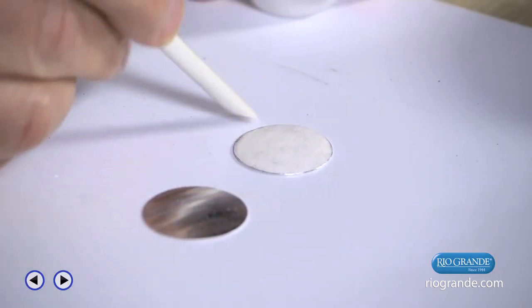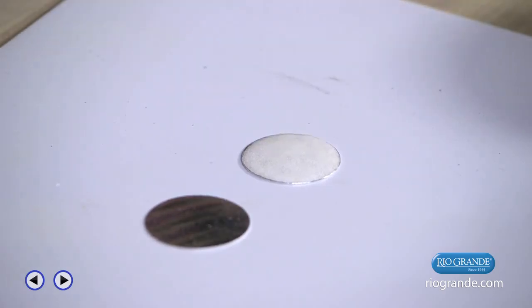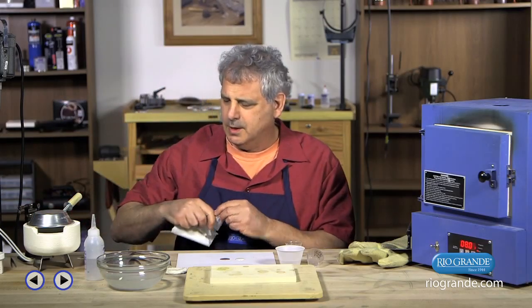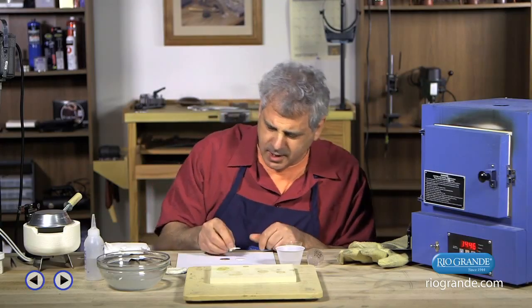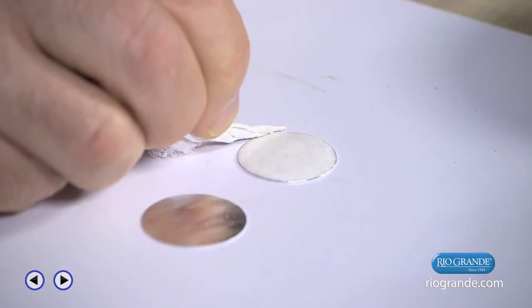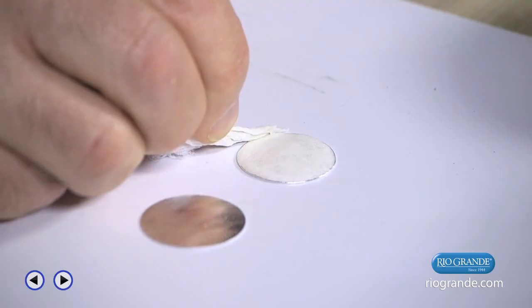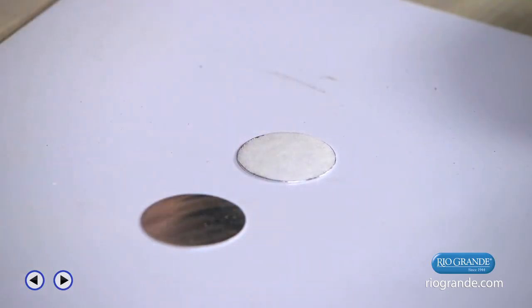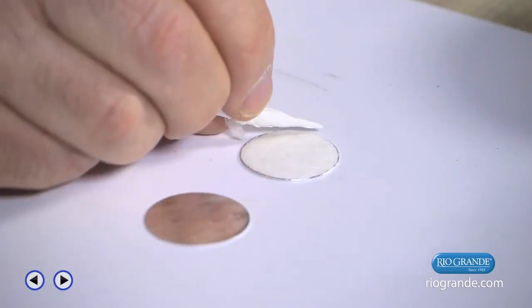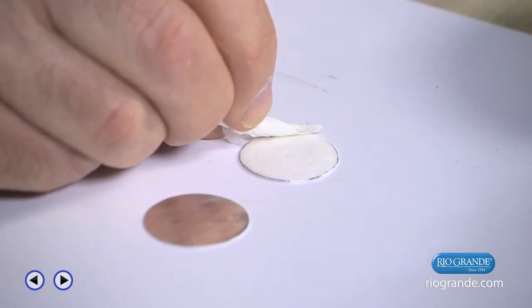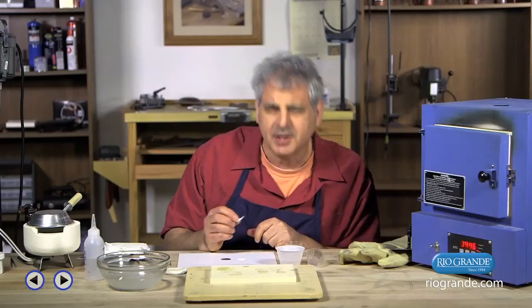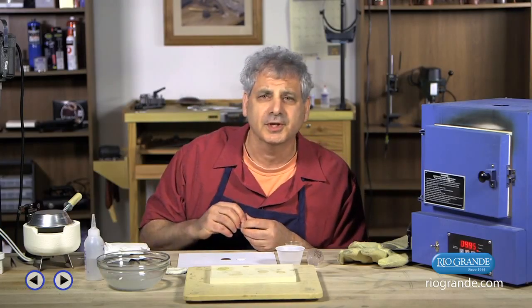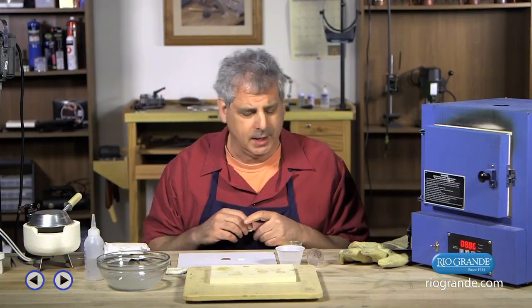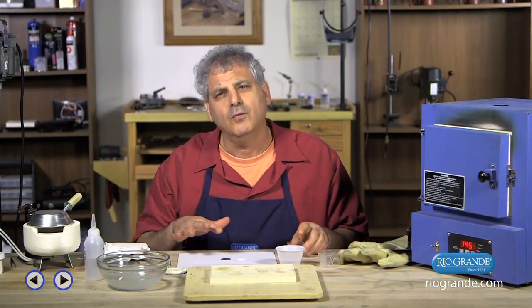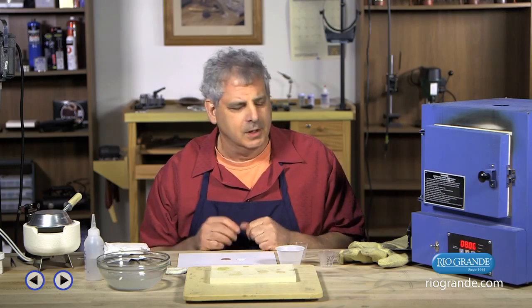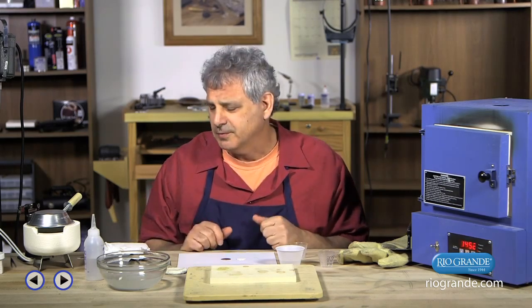And if I want to be a little fancy, I can do a little tap and that settles it a little bit. And now I'm going to take a little bit of toilet paper and make a little twisty, and very, very gently I'm going to blot the water. And what I'm looking for is the toilet paper to stop moving or turning dark with the water. And when that happens, I know I have enough of the water out to fire it. Most books will tell you you have to dry this completely, and that is incorrect, because there's not enough water in here to steam up and ruin the enamel. And I'm pretty impatient. I like to move quickly through these pieces.